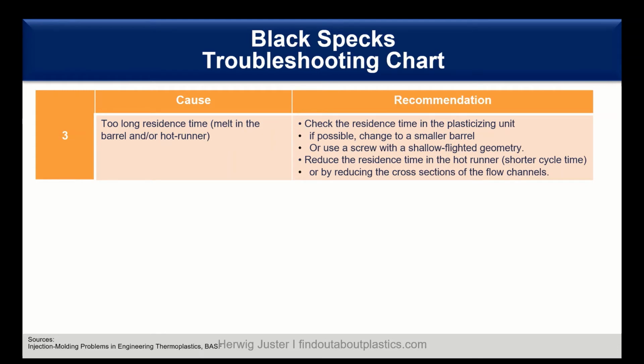Okay, then we also briefly touched already as one of the reasons is the residence time, so a too long residence time of the melt in the barrel and or the hot runner, which leads again to material degradation and forming of such black specks. So first thing as a recommendation is check the residence time in the plasticizing unit, see if that is okay. If not, try to change to a smaller barrel, or what also works is to use a screw with a shallow flighted geometry. Also one way to reduce the residence time in the hot runner is by shortening the cycle time, or by reducing the cross sections of the flow channels.